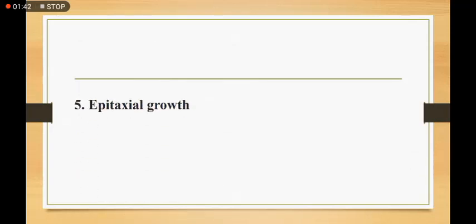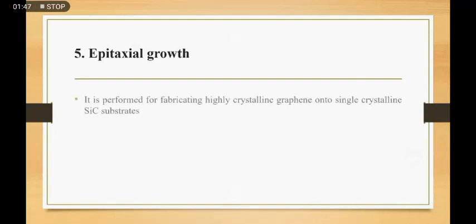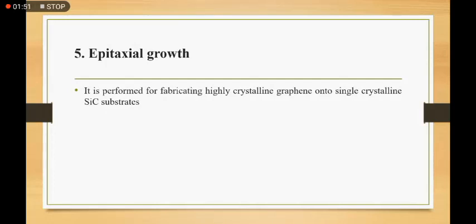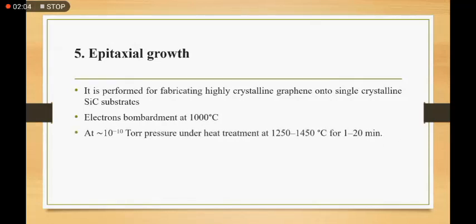Next, come to the fifth one, that is epitaxial growth, in which this process is performed by fabricating highly crystalline graphene on a single crystalline silicon carbide substrate. Several reports demonstrate the growth of graphene through sublimation of silicon from single crystal 6H silicon carbide. The growth process includes surface preparation using oxidation or hydrogen etching, followed by surface cleaning by bombarding electrons at 1000 degrees Celsius, and approximately 10 to the negative 10 torr under heat treatment at 1250 to 1450 degrees Celsius for 1 to 20 minutes. This growth process is based on the silicon sublimation mechanism at high temperature, which creates the anisotropy in graphene.